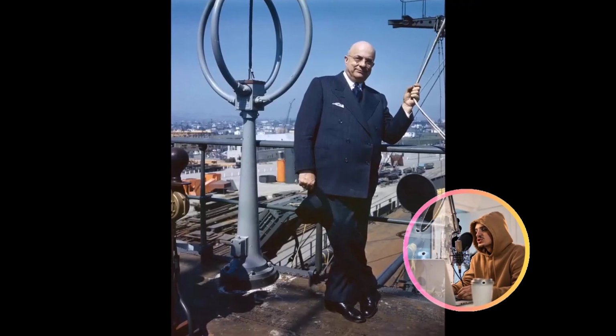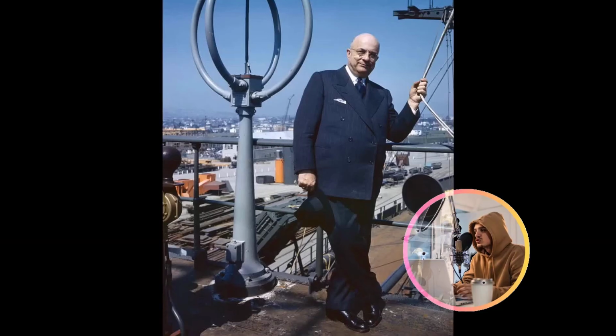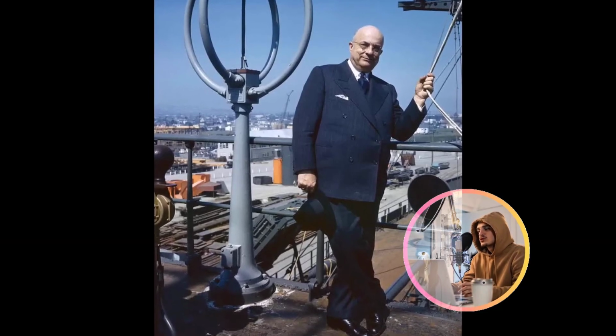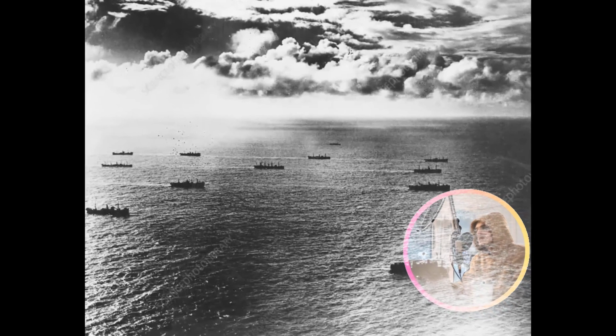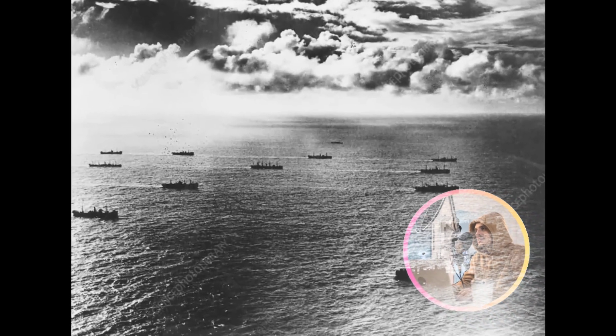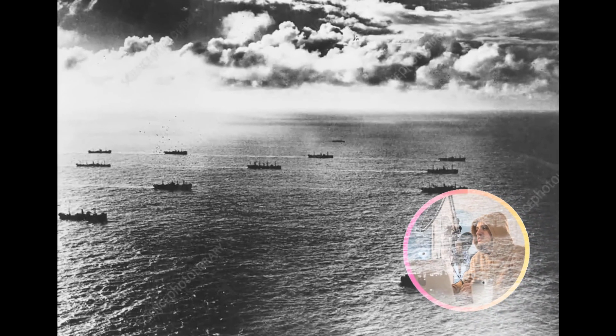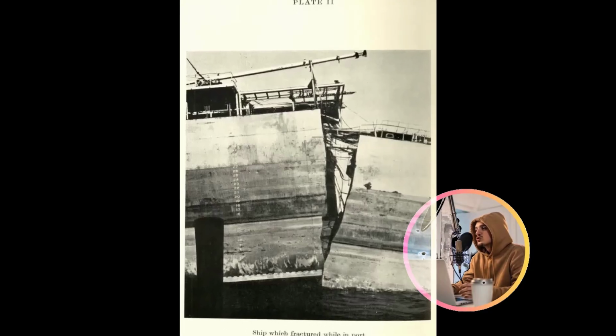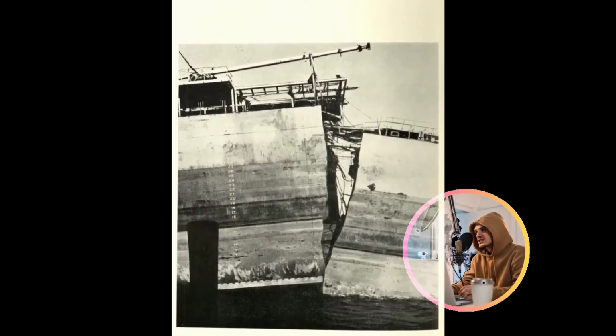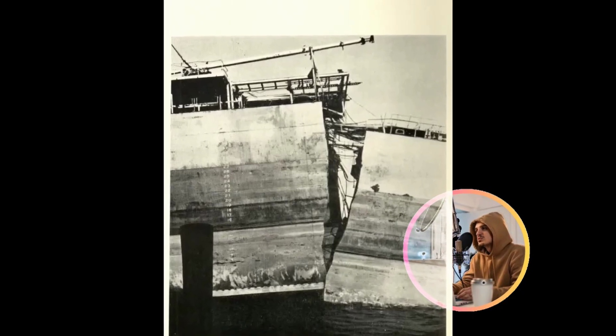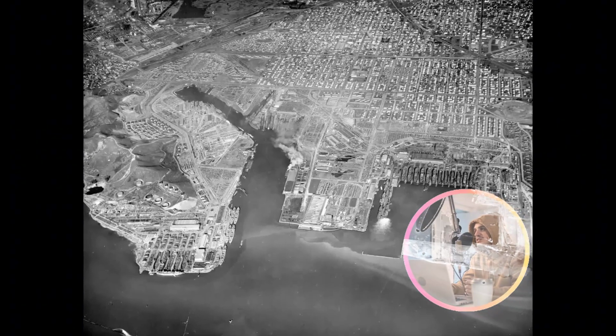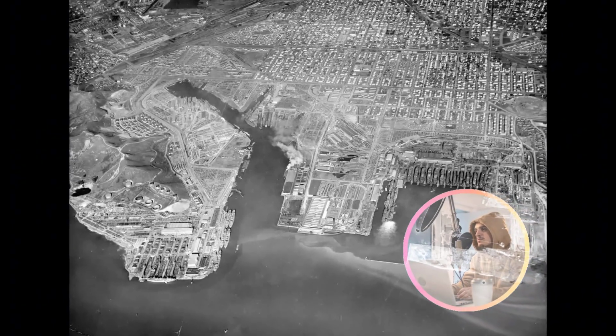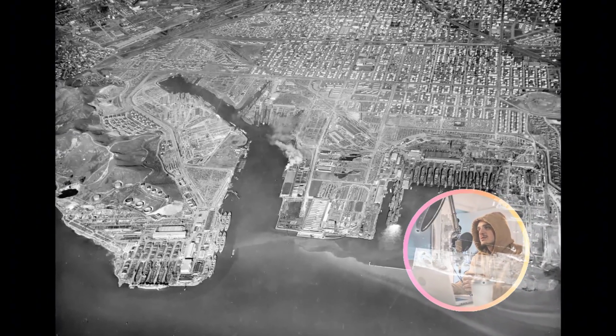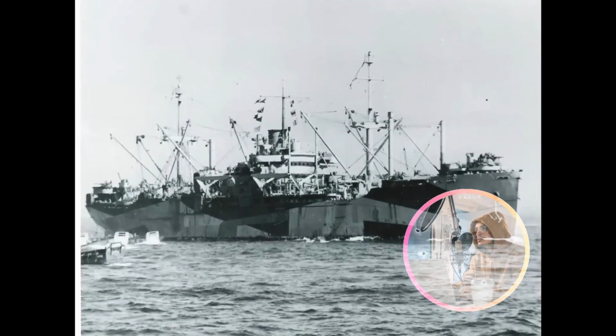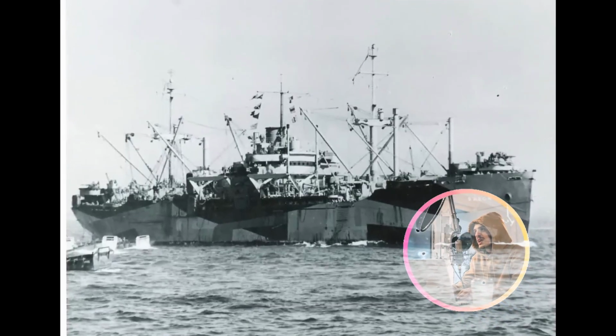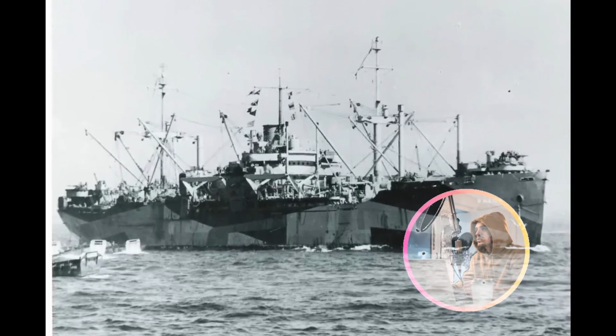In practical operational terms, this meant that a powerful wave impact that would inevitably initiate a dangerous crack in a Liberty ship would, in a Victory ship, merely induce a controlled flex within the hull, well within its normal, safe elastic limits. The hull plates themselves were ingeniously installed, incorporating sophisticated crack arrestor features directly into the fundamental structure. Rather than relying solely on continuous welds that stretched for hundreds of feet, Victory ships strategically integrated riveted seams at carefully determined intervals.